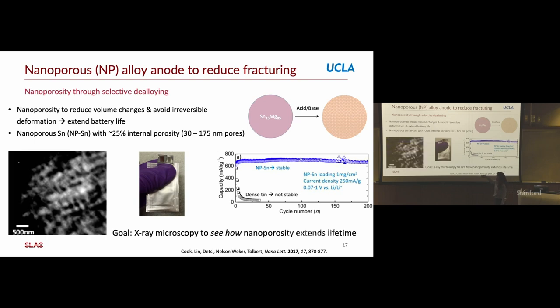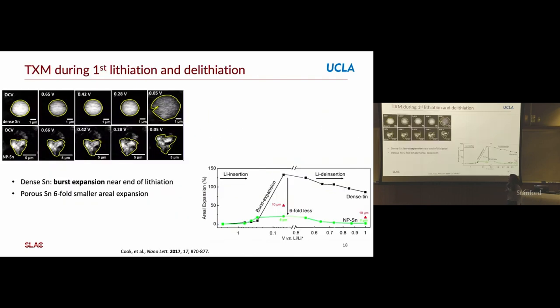And so we wanted to use X-ray microscopy to look at these anode materials while we cycle them. And so we used a pouch battery, very similar to what you would use in a standard lab. And we can cycle these for tens of cycles, if not hundreds of cycles. And we can use X-ray microscopy to see how those nanopores, which are shown here with an X-ray microscope, change as you lithiate it. And so this is something you can't do with a TEM or an SEM because those are in vacuum. They're very surface sensitive. You need very thin materials. So X-rays can penetrate very easily through these full batteries. Okay, so results.